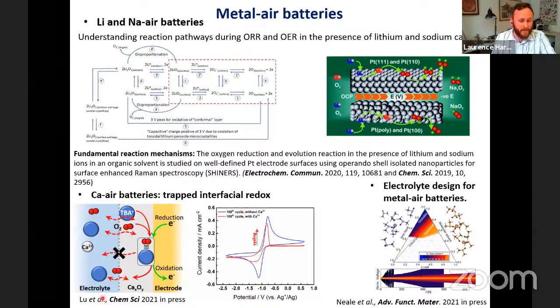And recently we've looked at calcium-oxygen electrochemistry, and something very interesting happens with calcium. Initially when you cycle it, I don't know if you can see this little dash here, this is the first cycle. It's very irreversible, but after cycling, you get a calcium oxide layer on your electrode surface, which ends up trapping your tetrabutylammonium oxygen species, and it becomes trapped within this very thin layer on the electrode surface.